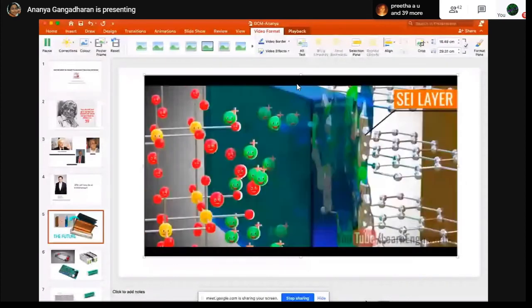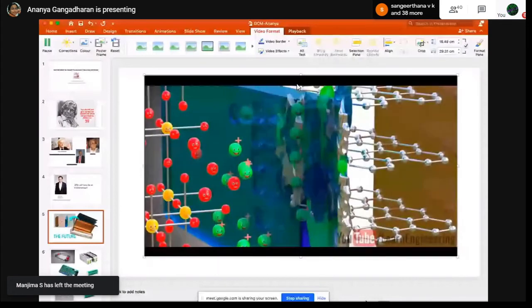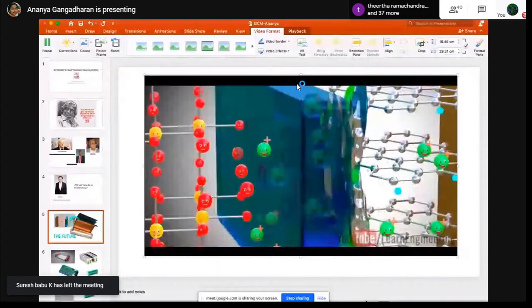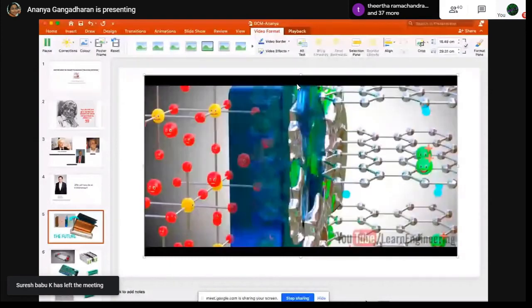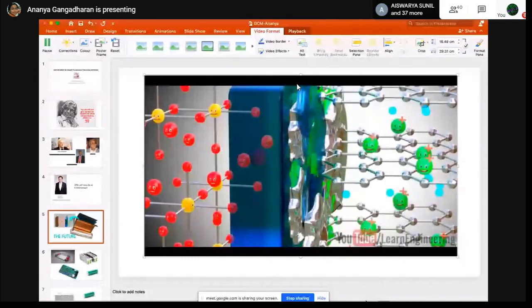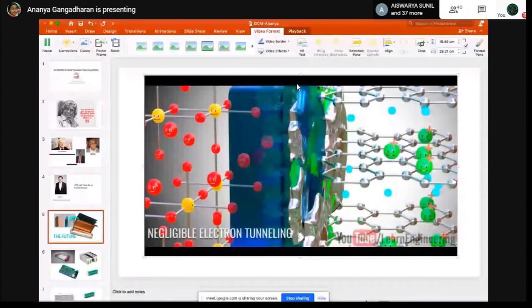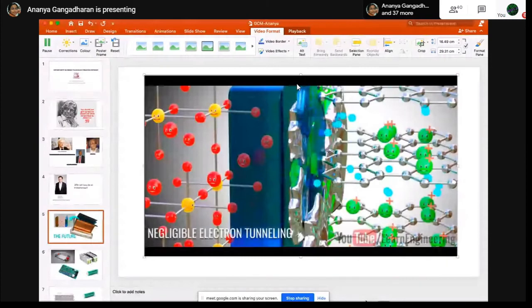The formation of this SEI layer is a blessing in disguise. It prevents any direct contact between the electrons and the electrolyte, thus saving the electrolyte from degradation. In this overall process of the formation of the SEI layer, it will consume 5% of the lithium. The remaining 95% of the lithium contributes to the main working of the battery. Even though the SEI layer was an accidental discovery, with over 2 decades of research and development, scientists have optimized the thickness and chemistry of the SEI layer for maximum cell performance.